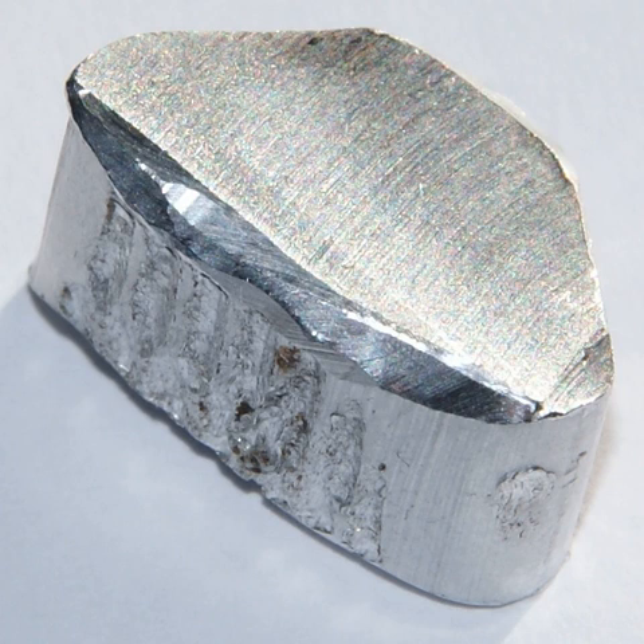Anodes of the electrolysis cell are made of carbon, the most resistant material against fluoride corrosion, and either baked in the process or are pre-baked. The former, also called Söderberg anodes, are less power efficient and fumes released during baking are costly to collect, which is why they are being replaced by pre-baked anodes, even though they save the power, energy, and labor to pre-bake the anodes. Carbon for anodes should be preferably pure so that neither aluminium nor the electrolyte is contaminated with ash.